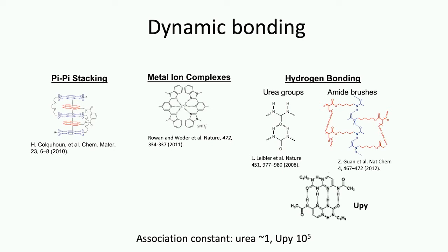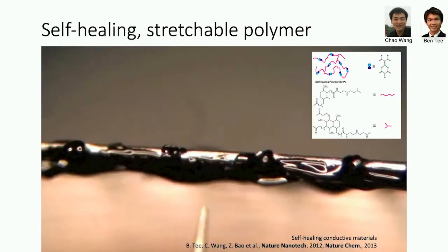And the latter essentially allows us to tune the mechanical property, and the weaker ones allow us to incorporate an energy dissipation mechanism into the material. So combining these different chemical bonds allows us to achieve the desirable mechanical property and also potentially realize electronic property. So this is an early version of the material that we have developed.